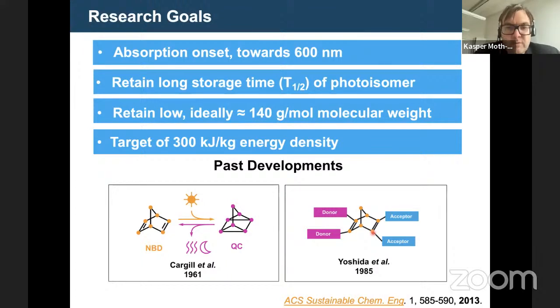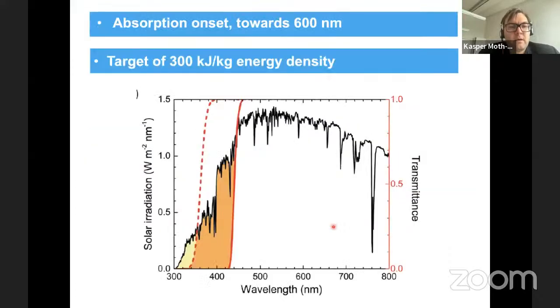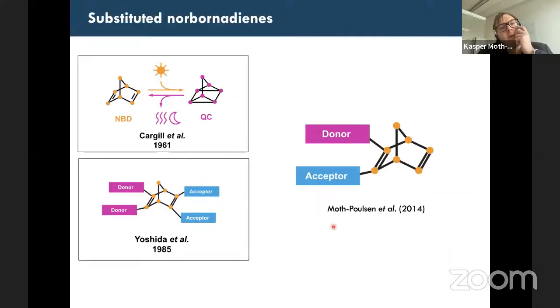But we wanted to see if we could improve the properties. In the first analysis of this, you can see that there are 2 donors and 2 acceptors. And if you want to reduce the weight, we thought maybe we could remove 1 donor and 1 acceptor and put it in another arrangement. So this is our molecular design. We had the original system, the donor acceptor system by Yoshida, and then we thought we could make it simpler and lighter by putting the donor and acceptor on the same side of the molecule.